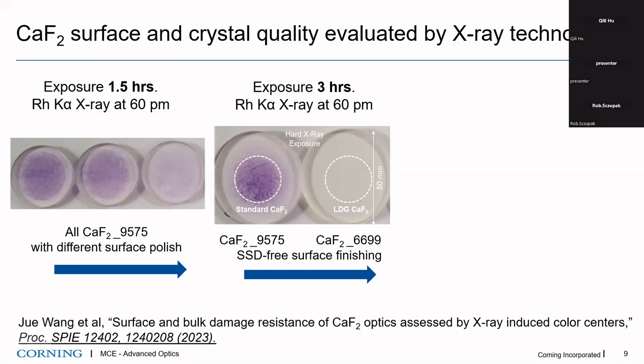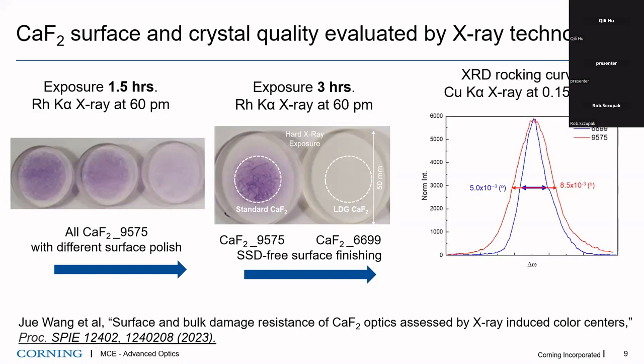We compare optical grade on the left to the laser durable grade after 3 hours of X-ray. By comparison, you can see the durability improvement, right? We also conduct an XRD rocking curve to compare. Basically the concept is, if the crystal is better, we should get a narrower full width at half maximum at the X-ray diffraction peak position. Right?